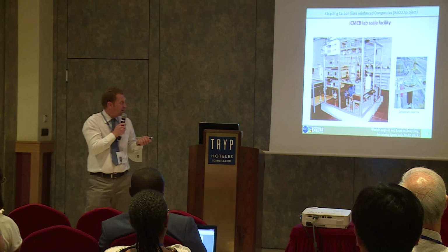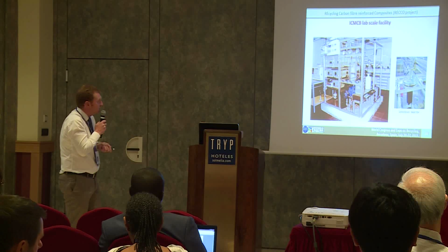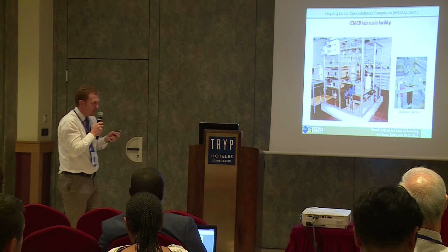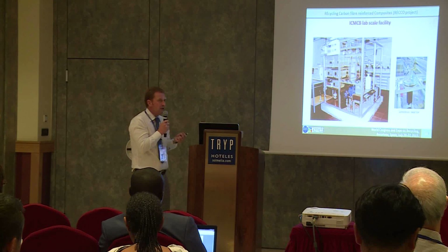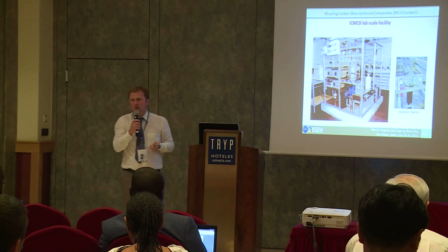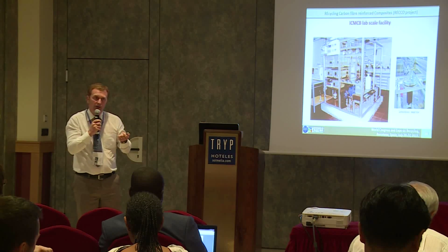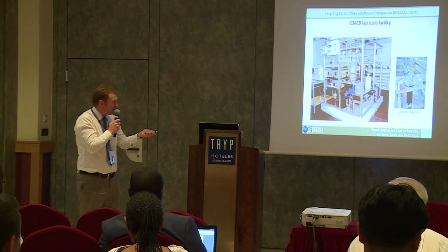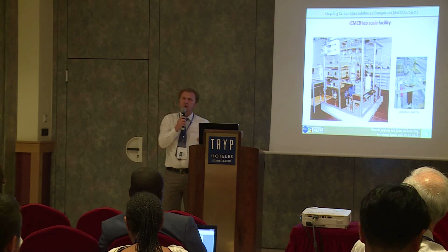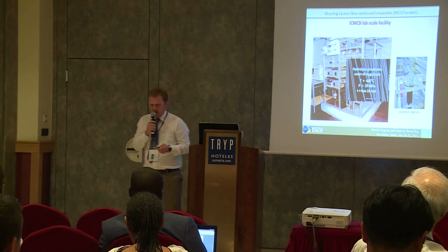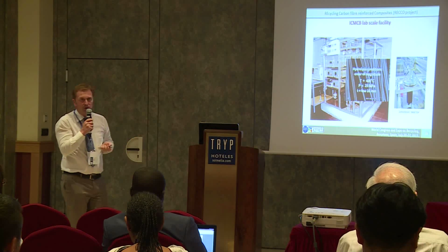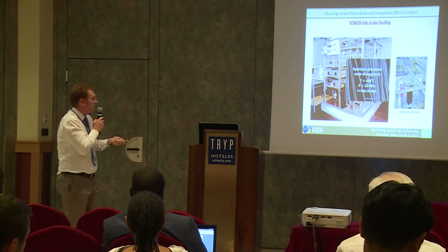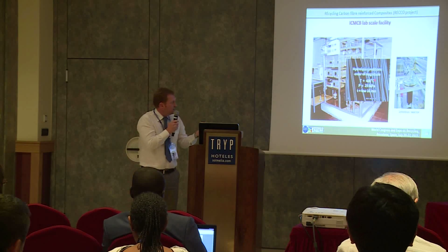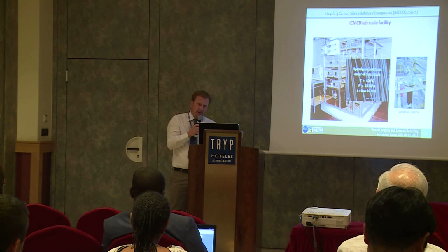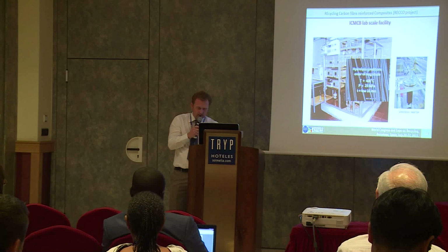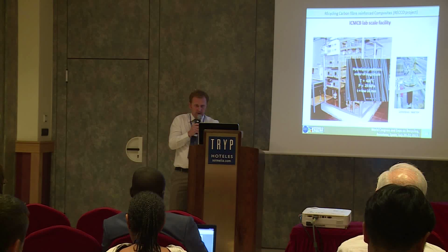Regarding the chemistry, we did the experiment on our lab scale facility. This is the solvolysis reactor, and in terms of principle it is relatively easy. We put the composite material into the reactor, and we are just making a reactive extraction. We are flowing some water into the reactor in specific conditions of pressure and temperature, and at the end you can recover the carbon fiber, which is very clean. You see here the conditions, about 400 degrees Celsius, 25 MPa, and the reaction time is, as I told you, fast, less than 10 minutes. So it's fast if you compare with other kinds of technologies.